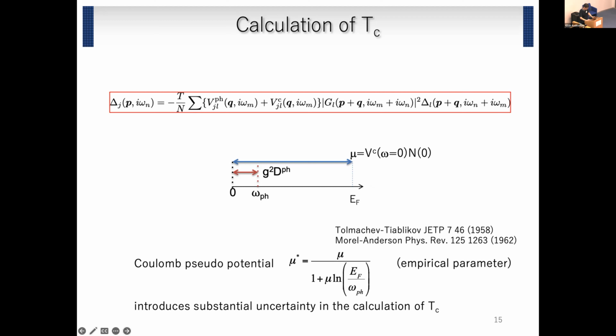And so usually we introduce this empirical parameter mu star. But as was discussed in several talks in this workshop, here we have some not well-defined factor, and this introduces some substantial uncertainty in the calculation of Tc.